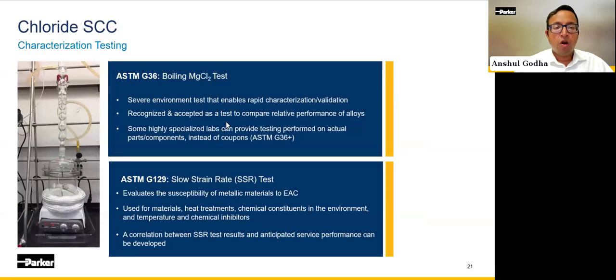While there are several ways of testing for chloride stress corrosion cracking, the most common chemical test that is applicable to offshore alloys is the ASTM G36, which is a boiling magnesium chloride test, which can be done both in the form of coupons or with slight modification to the test. It can actually be done in finished parts, but only by very highly specialized labs. The other common method of testing for chloride stress corrosion cracking is a mechanical test where there is exposure to chloride ions during the test, but also there's a slow strain rate test, a load that is being applied to the material. And this can be a very useful test as well.